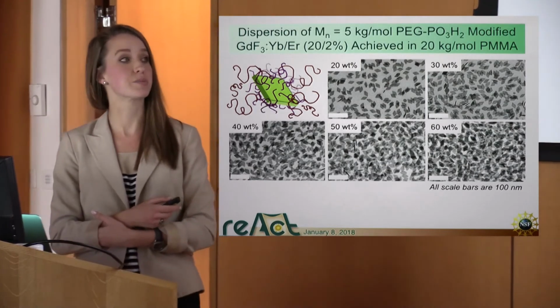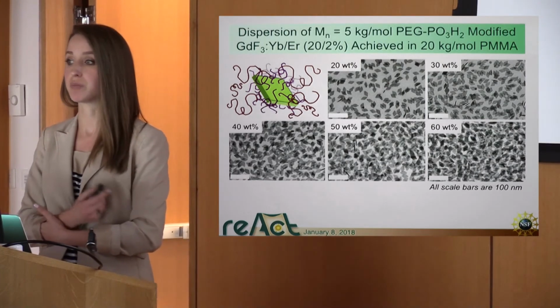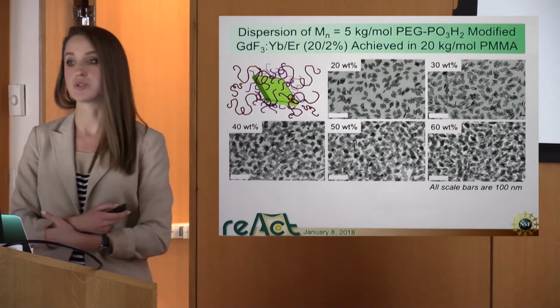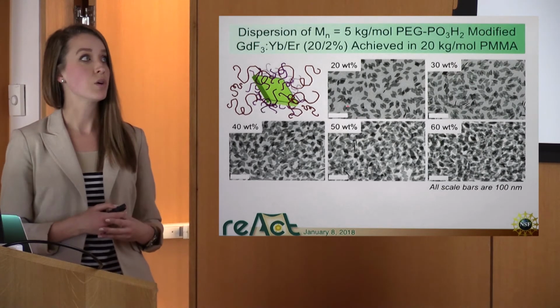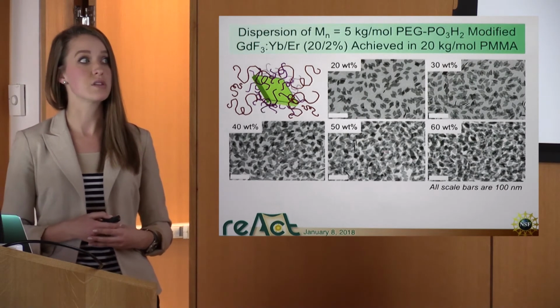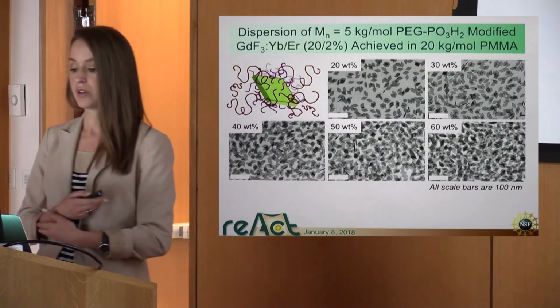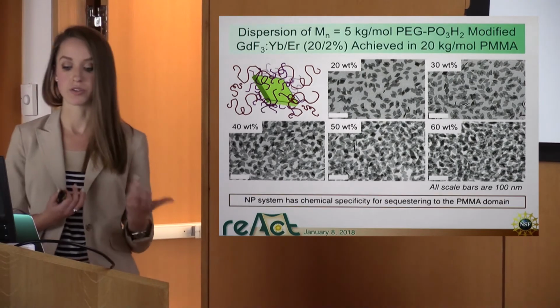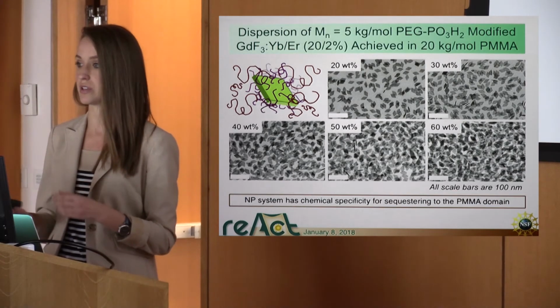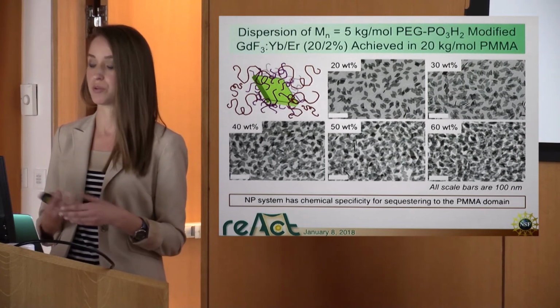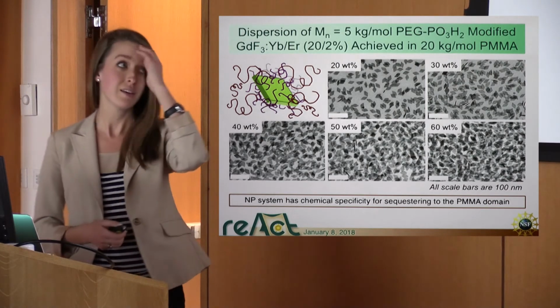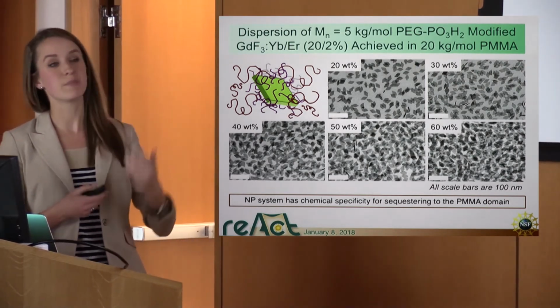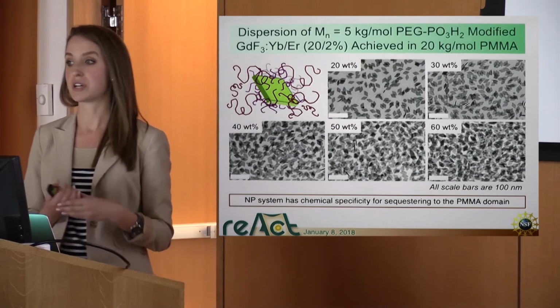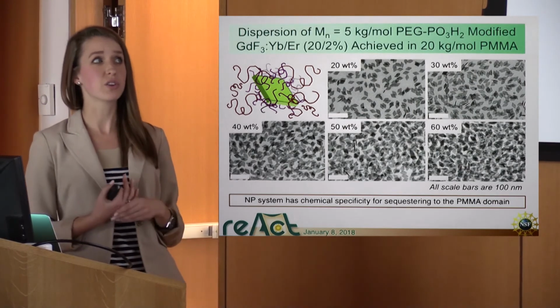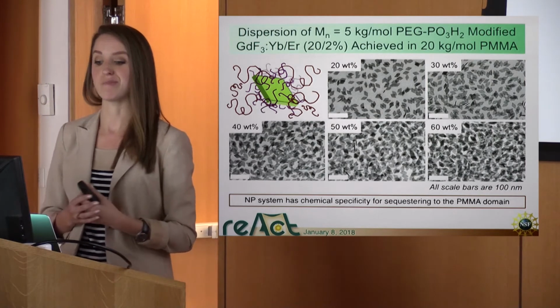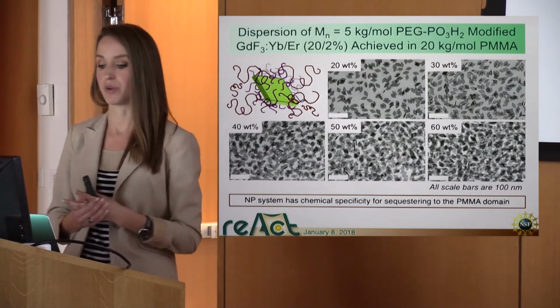This is the dispersion of these platelets with PEG on their surfaces in a 20K PMMA matrix with increasing loading. We can see here that these are quite well dispersed. And as I mentioned, the nanoparticle system now has a chemical specificity to one of my domains, the PMMA domain in my block copolymer. You can look at these TEM images, and again, these are top-down images, and say they look pretty dispersed, but they also look like they're pretty parallel to the surface already.